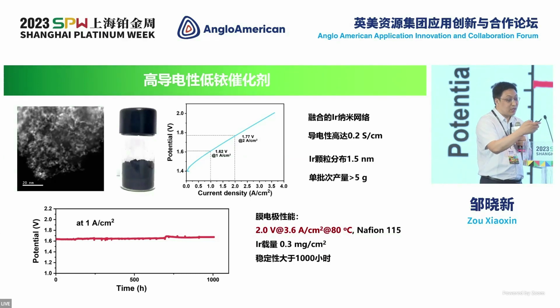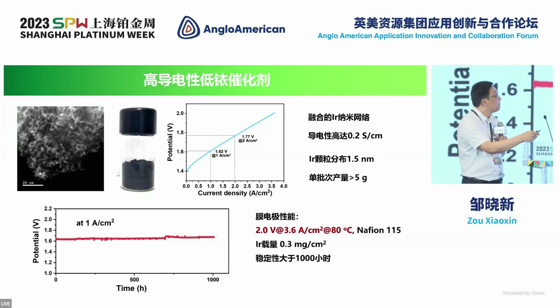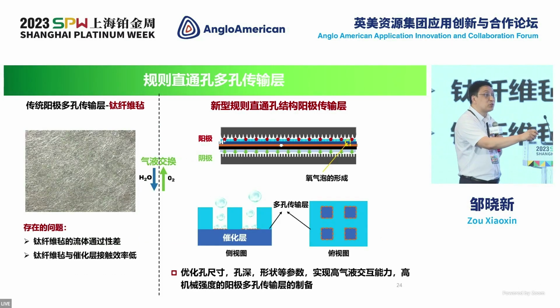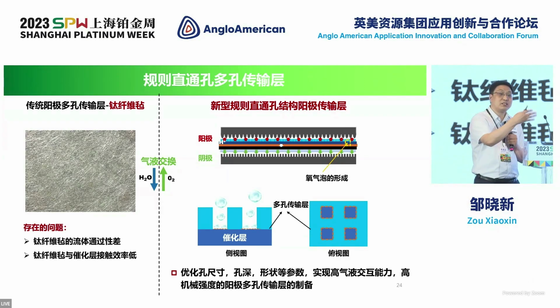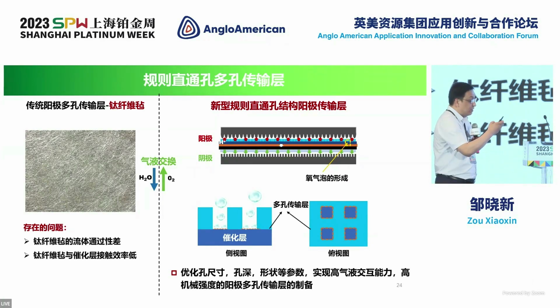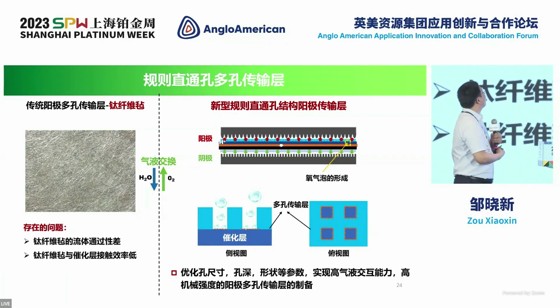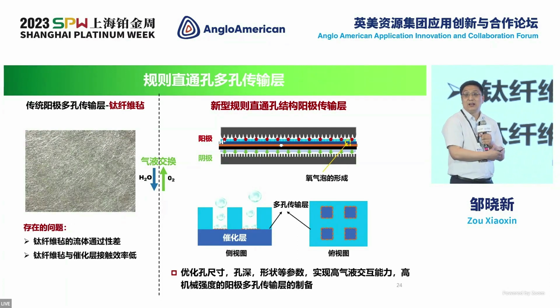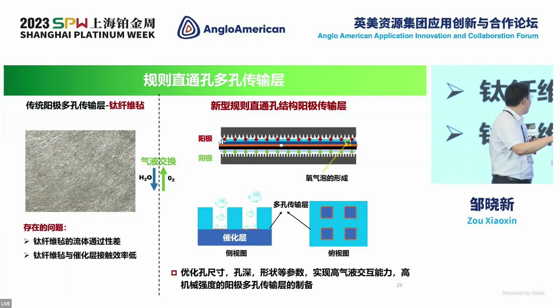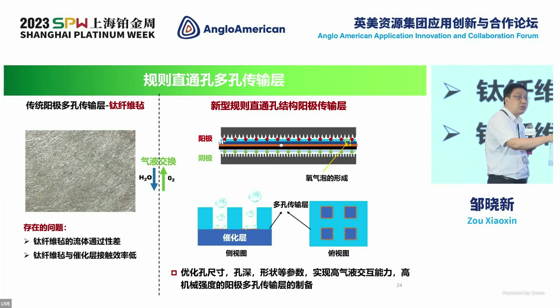And its membrane electrode performance is 2 volts at 3.6 A per square centimeter at 80 degrees Celsius. And another possibility is to develop the porous transmission layer. And the most used is the titanium fiber cloth. So there are a few problems with this technology.